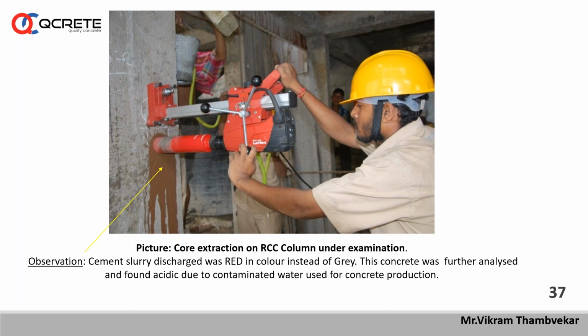Then further we analyzed this hardened concrete in our laboratory, and we found that the pH value was very less as per the requirement. And when we tested with chemical analysis, we found the concrete used for casting all these columns was a little acidic. The pH value was less than about 4 or so. So I want to explain here, these things happen only because of the use of contaminated water. Anybody who is using bore water or well water should take care of testing it properly for all these chemical components before using it for fresh concrete. Of course, pH value is a very simple test, but one has to perform it before using the water for making fresh concrete.